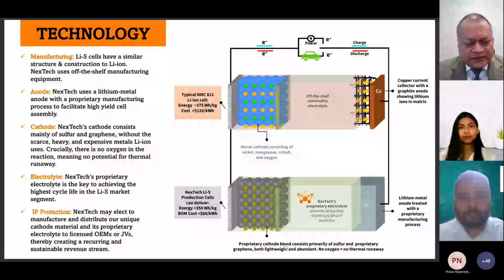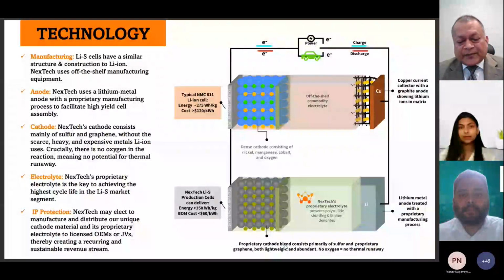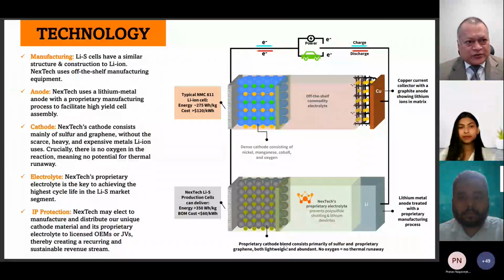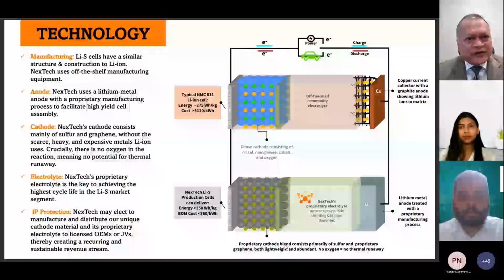So the assembly of the cells becomes very much easier than the standard cells. Cathode, you have mainly sulfur and graphene. So the cathode is very light compared to the traditional cathodes. Obviously, anode, pure lithium foil, very light again. So if you look at it, there is no oxygen in the cathode. It's sulfur and graphene. So when the battery becomes hot and the separator melts, you short the battery out, the battery will not go into thermal runaway because there is no self-sustaining oxygen inside the cell.